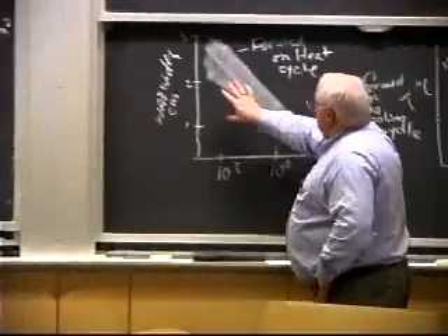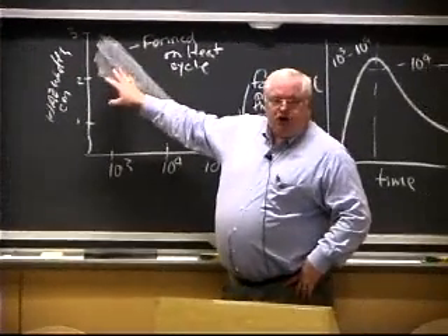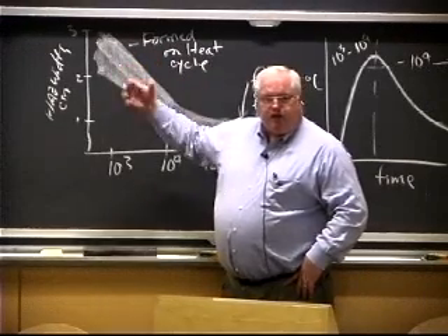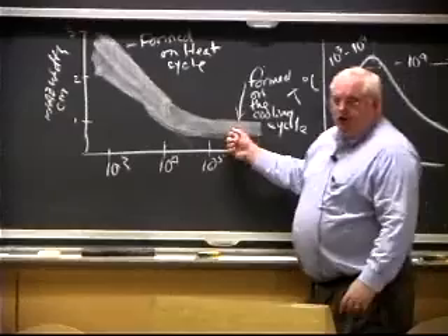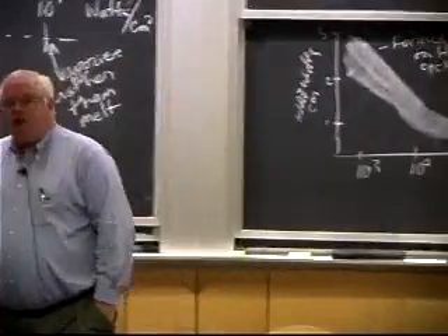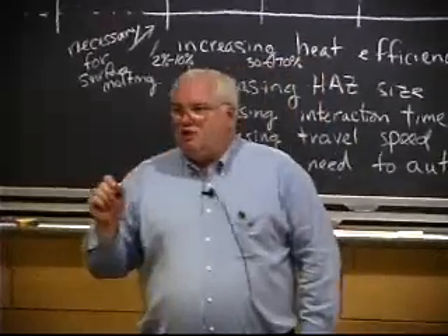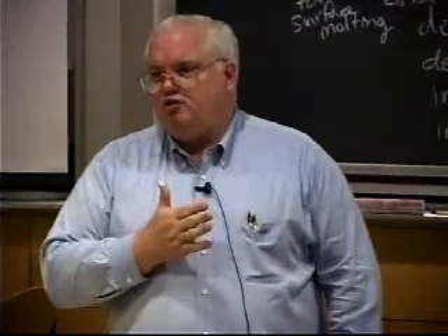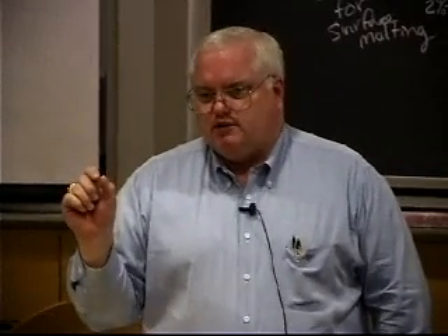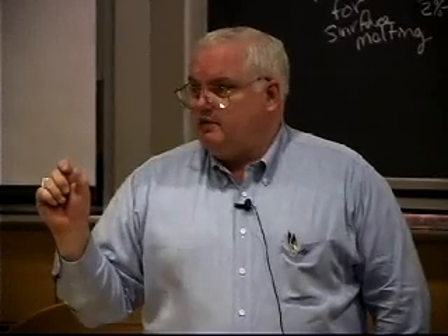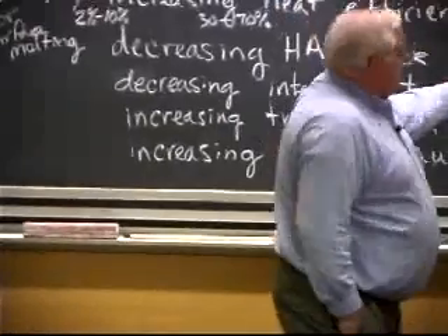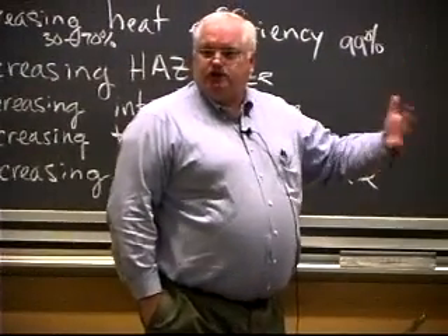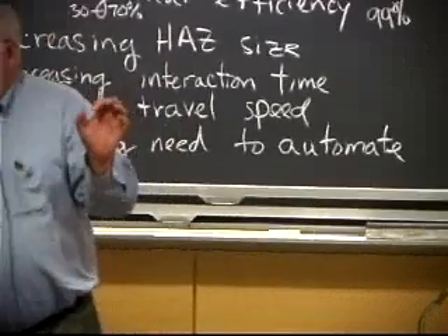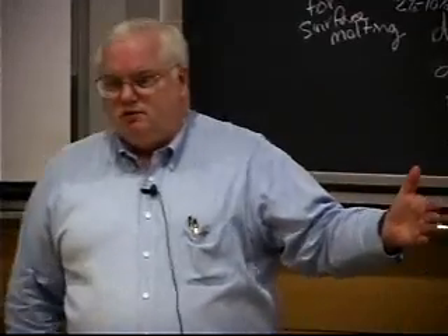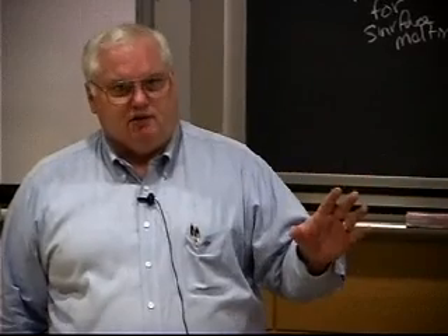So it turns out that over in this region, the heat affected zone size is directly proportional to the time that the heat source is present, whereas over in this region, the heat affected zone is really related to the width of the material that I melted, because that determines how much heat has to be carried out by cooling. If I make an electron beam weld and it's 1 millimeter wide, I'm going to have a narrower heat affected zone than if I make an electron beam weld that's a centimeter wide. They're both 99% efficient, but obviously one of them has 10 times as much heat input as the other. If it's nearly 100% efficient in melting, but one of them melts 10 times as much material, it's going to take 10 times as long to cool. And that's going to grow the heat affected zone on the cooling cycle. And so